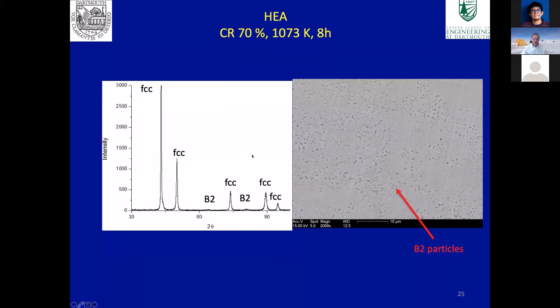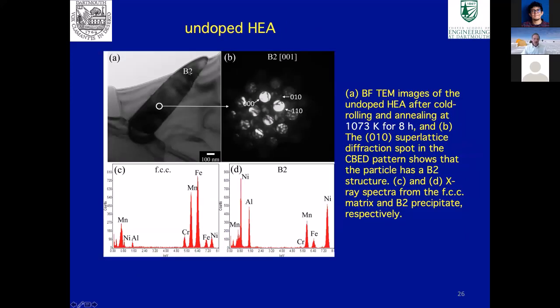This shows the carbon-free material. And you can see these particles all throughout here, and in X-ray diffraction. If you look in the TEM at some of these particles, you can see one of these particles here, which corresponds to a B2 phase. And if you look at the chemistry, the particle itself has much more nickel and aluminum than the matrix, which is mostly iron and manganese with some chromium.